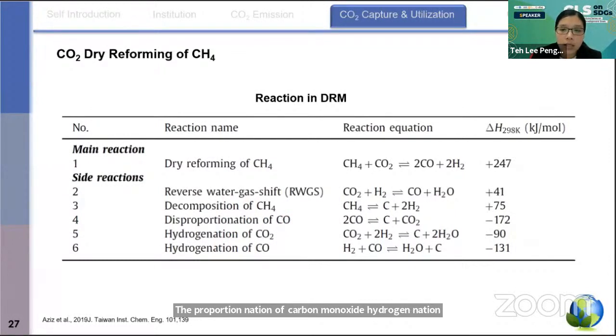So DRM is a very thermodynamically favorable reaction. Usually it happens above 700 degrees C. So these are very high temperatures. It promotes the DRM route, meaning it promotes these main reactions and inhibits the side reactions. However, from the economic and technical perspective, it would be very good if we can lower the temperature below 700 degrees C. In order to do that, very active, stable and very selective catalysts need to be introduced into this DRM system.